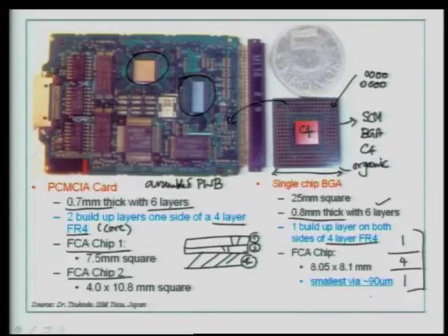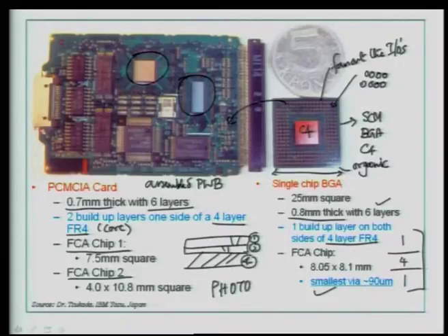Now, in this particular case of single chip module BGA, as I mentioned in the packages chapter, the function of the substrate here is basically to just fan out the IOs through the organic substrate into the BGA balls at the other side of the package. The flip chip size here is almost 8 by 8 square, and the smallest via used here at that time is around 90 microns, which is a very remarkable achievement considering that this was the beginning of these kind of concepts. Today, using laser drilling, and by the way, this process used photovia method, but today people are using laser drilling to achieve 60 micron or even 50 micron drills.